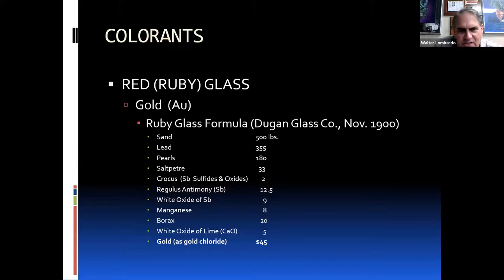Other antimony sources include antimony oxide, which would be minerals like cervantite and things like that, a little bit of manganese, a little bit of borax, which is basically the flux to help it melt, and white oxide of lime, which is just your typical lime like you'd use in cement. And it also said gold. It's interesting, in those days they didn't use an amount by weight, but by the dollar value. So in this case, for a 1,000 pound batch of glass, they'd use $45 worth of gold. Now, at that time, gold, I believe, was probably $16 an ounce. That was almost 3 ounces of gold that had to be used to make the ruby formula. So you can see that's a little expensive compared to the typical things they might have used. In fact, that was probably worth more than all the rest of the ingredients combined.